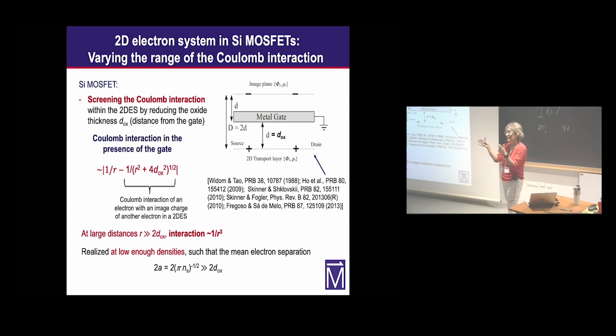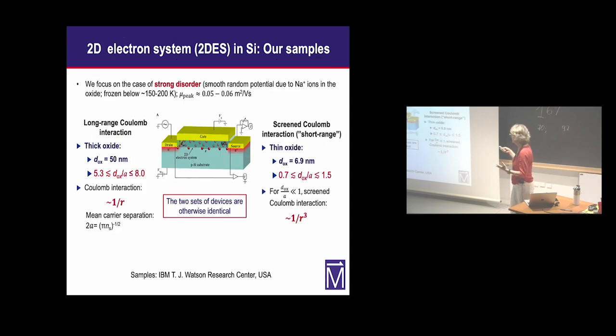On the other hand, if the gate is very close, such that the distance to the gate is smaller than the mean carrier separation, then this interaction assumes a dipolar form. And this condition can be reached, obviously, more easily at lower carrier densities. So this is what we have used to investigate the effect of the Coulomb interaction on the dynamics of this system. So we had two sets of silicon MOSFETs.